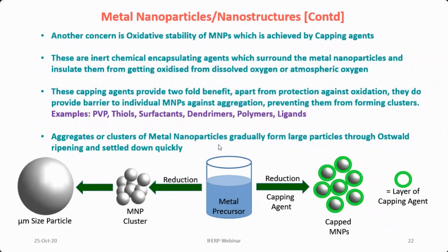There are certain surfactants used, which are surface active molecules. They form a layer on the metal nanoparticles and prevent aggregation. In some cases, dendrimers have been used, polymer matrices have been used, and certain ligands have been used. These ligands are known to bind metal strongly, and their metal binding properties have been exploited to use them as protecting layers. Otherwise these aggregates or clusters of metal gradually form large particles, so to prevent that, this is done.